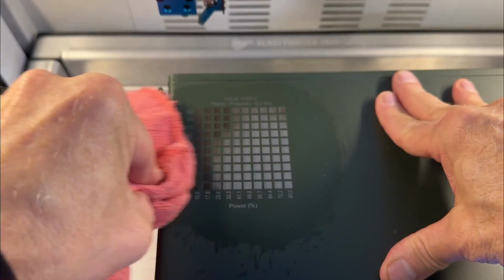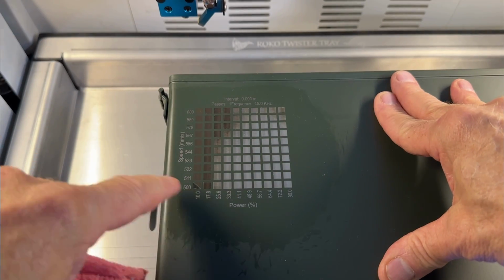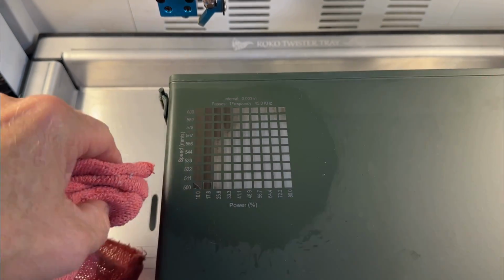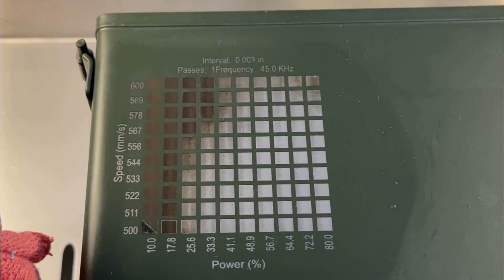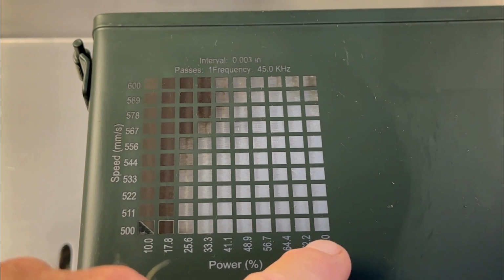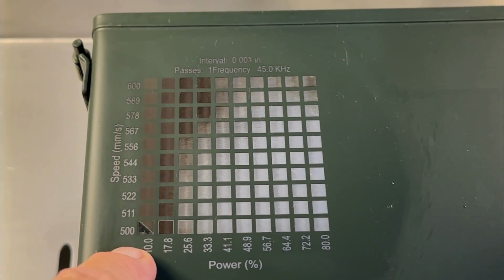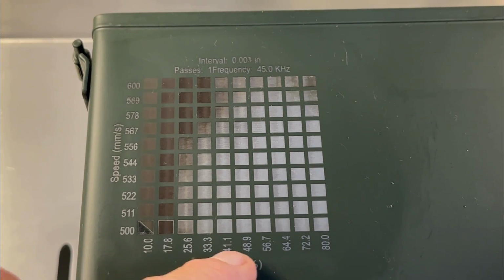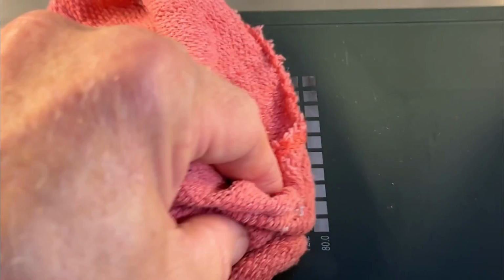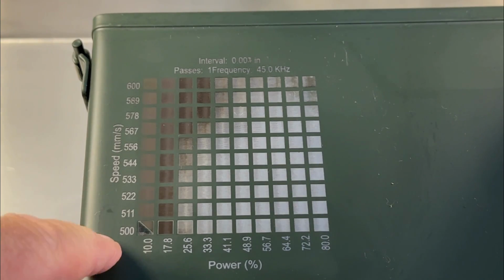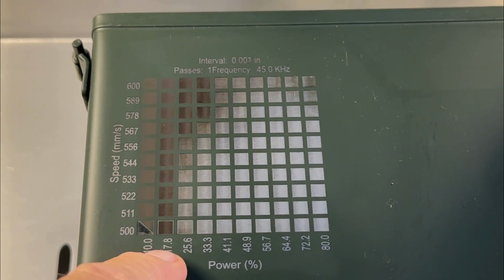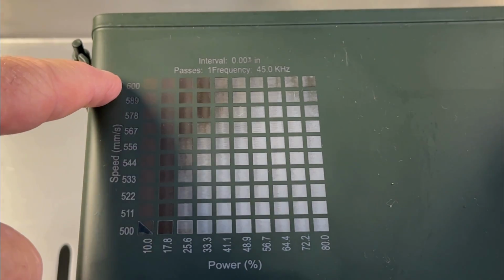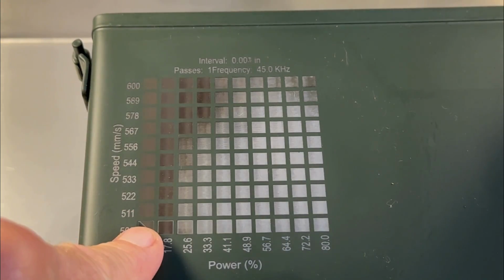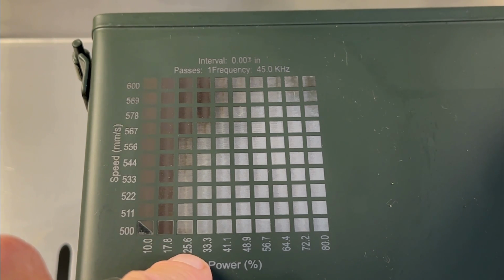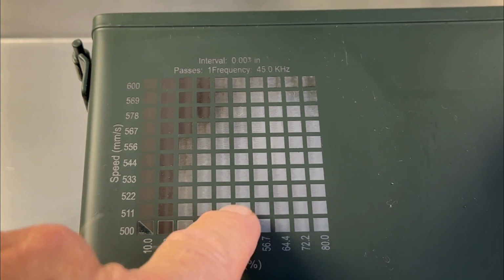See what we got going on here. Well, it doesn't look like we're going to be able to do much as far as, let me zoom in on this a little bit. You can see that my settings for tumblers, which is 600 millimeters and 80% power, get all the way down to the bare metal. That's not a problem. And I was fairly confident that that was going to happen. And you can see kind of the 10 to 20% worth of power, no matter whether we're going 500 or 600, you're not going to penetrate the paint. Once you get up past 25%, you're going to start burning that paint off.